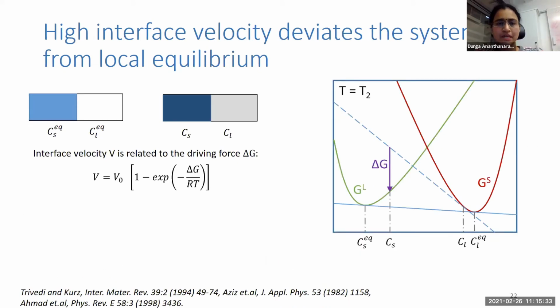But what happens at very high interface velocity? We go completely away from this equilibrium composition. We will have something very different from equilibrium composition in the solid and in the liquid. To understand this, we look at the Gibbs energy curves again. Suppose we go away from equilibrium and have, let's say, a liquid composition Cl, then the driving force for forming a solid of composition Cs is given by this delta G. The interface velocity is related to this driving force delta G by this equation, where V0 is the speed of sound. And then we see that we go to a completely different composition regime.